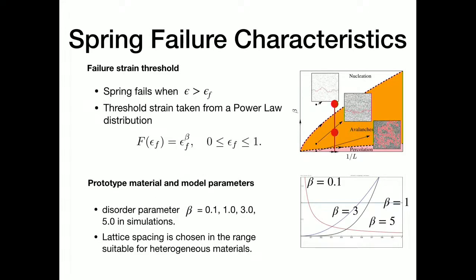So the spring failure criterion is when the strain in the spring reaches a critical value. For the initial part of the study that I am presenting, I'll be using the critical strains drawn from a Pareto distribution, just like the random fuse model of Shekhawat et al. And we would like to look at the effect of disorder on the record statistics and any interesting parameters that we can see. We look at these cases just like them, and these are the density functions.